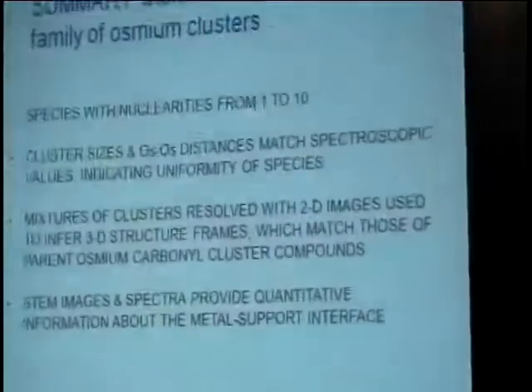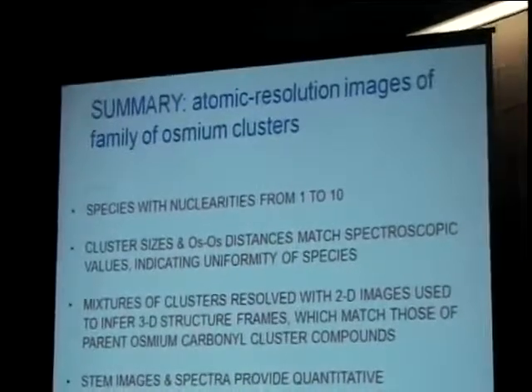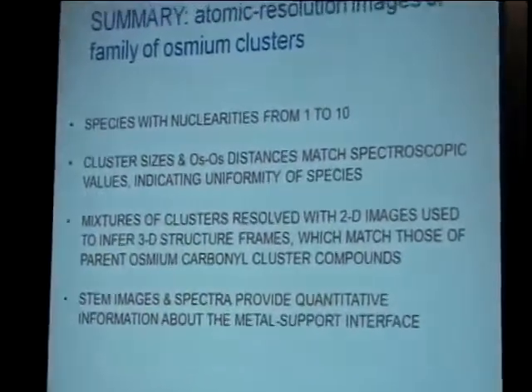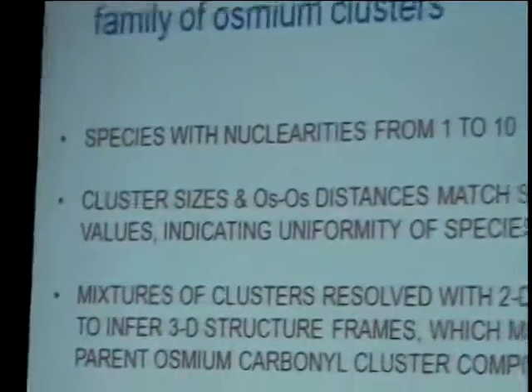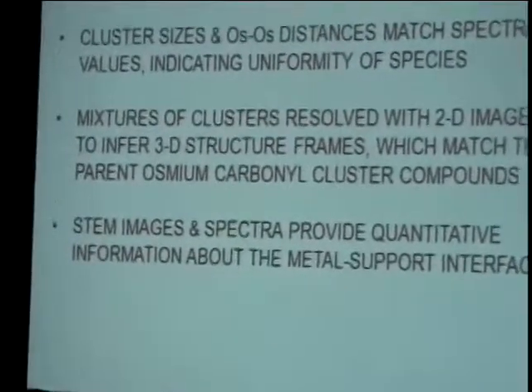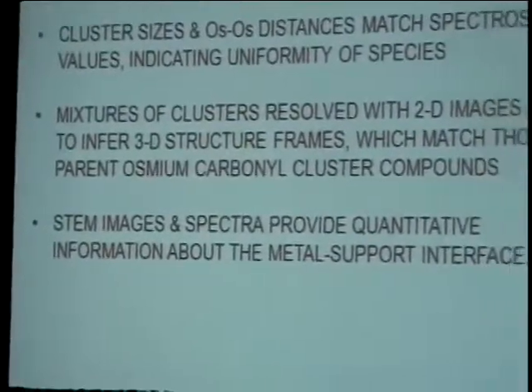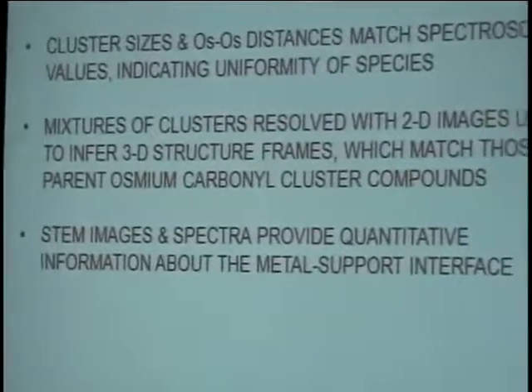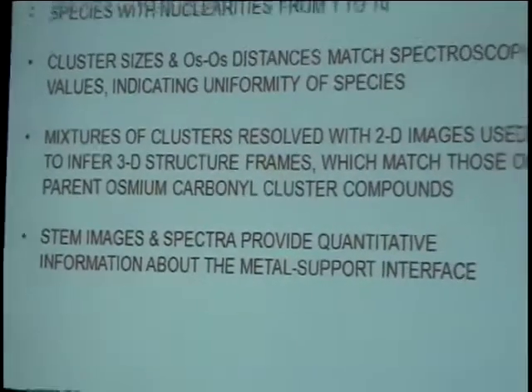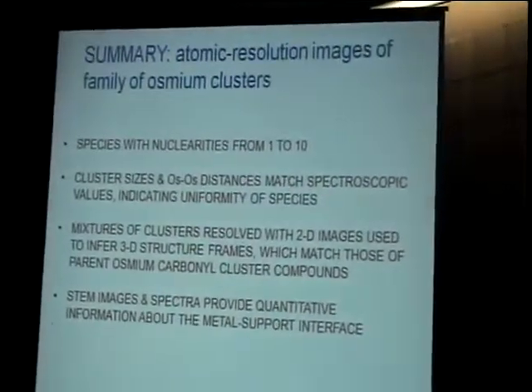So I want to summarize what we're doing here. By using aberration-corrected STEM, we're now able to make in high yields and fish out species with nuclearities going from 1 to 10, because of the opportunities afforded by the chemistry of osmium carbonyls. We can determine cluster sizes and metal-metal distances. Matching those, we determine spectroscopically, which is evidence that the syntheses have been done precisely. And then we can resolve mixtures. The point I should emphasize is that they're 2D images used to infer 3D structures. So there's clearly an inference there.